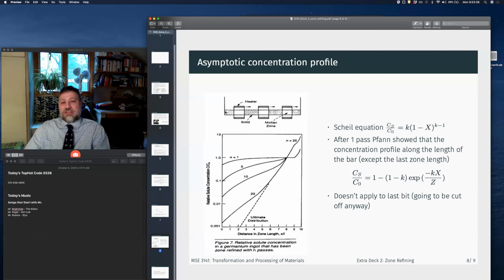So this isn't used to go from say 5% purity. This goes from what would be considered commercial purity of 99.9% or higher to ultra high purity, 5 nines, right? So this goes from three nines to 5 nines, essentially, or concentrations that you can get from normal casting processes to compositions that you need for electronics.